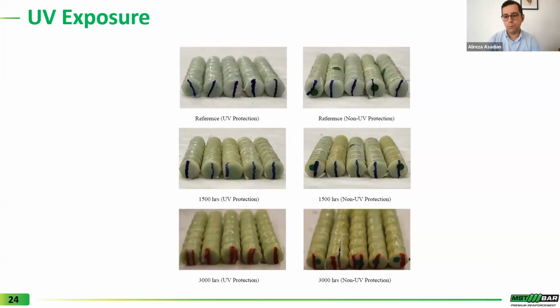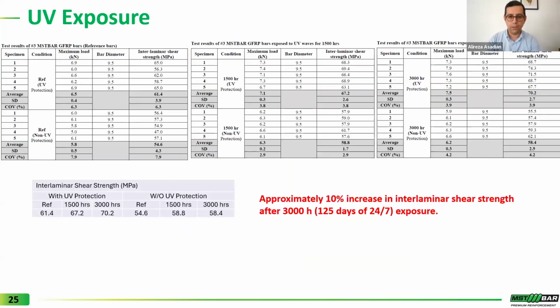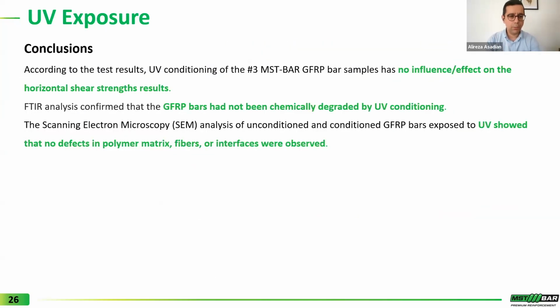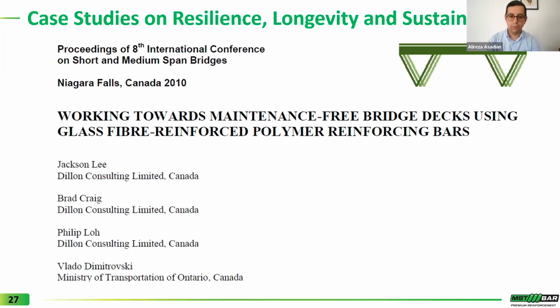As you can see in these pictures, some discoloration was observed as a result of exposure to UV lights. However, there was no degradation in terms of mechanical properties on the rebar, and this report concluded that there was no effect on the horizontal shear strength of MST bar due to UV exposure. The FTIR analysis confirmed that GFRP bars had not been chemically degraded by UV conditioning. Also, the SEM analysis of conditioned and unconditioned GFRP bars exposed to UV showed that no effect in polymer matrix or fiber or the interface were observed.